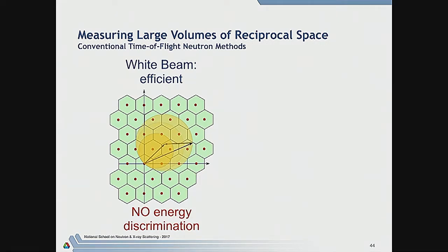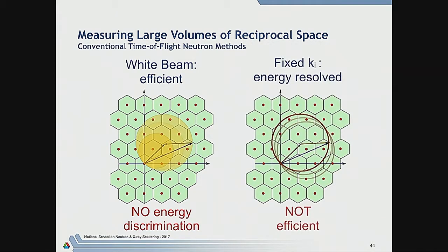But it doesn't provide you with any energy discrimination. But if you have a fixed ki, as in a chopper machine like ARCS or SEQUOIA, in principle you could also fill space, but you'd have to rotate the sample because you're measuring on a single Ewald sphere, and you'd have to rotate the sample in order to fill the volume instead of just measuring on these spherical surfaces. Okay, so could we do both?